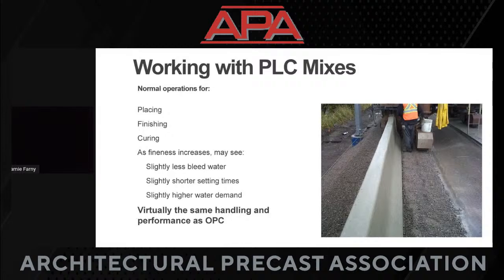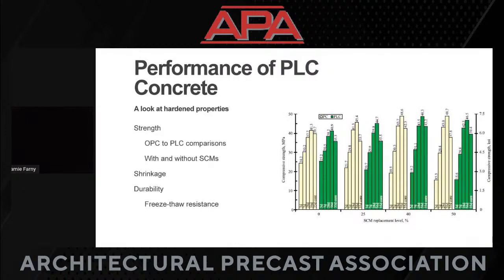This is pointing back to that importance of knowing your materials and your mix designs and testing, understanding them. The message here, though, is it's virtually the same handling and performance as ordinary Portland cement concrete. It's designed to be that way. You have the technology that you use with OPC mixes. You can turn to that same kind of approach for a PLC mix. And that picture I'm showing at the right is a zero slump barrier wall made with PLC. It's up in Canada. It's been performing really well. So again, we can take these from normal workability kind of mixes down to the very low workability mixes, and stiff and extruded, and they can still perform well.